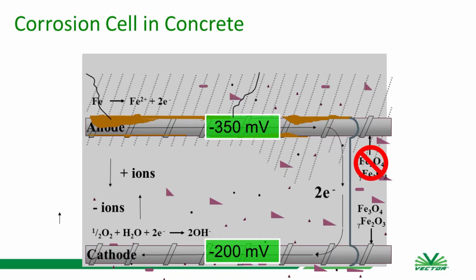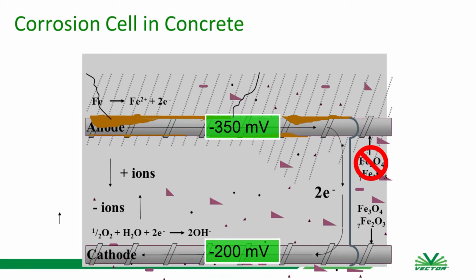So that energy is being given off in the form of electrons. When electrons are being given off, those are negatively charged. And as that area starts to corrode, it's called an anode. An anode's where the energy is leaving from in a corrosion cell. So your anode will start to form. Those electrons will be given off. They'll flow down some metallic pathway. That steel could be from here down to here. For this illustration, we're going to use the bottom mat. And then a cathode will form, or a cathodic area.